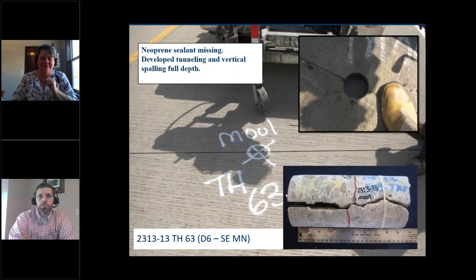Another one, the sealant happens to be gone. This one is early in our transition to water cement. You could actually see the water sitting in the core hole, so this wasn't draining very well, but we are starting to see a little bit of deterioration.